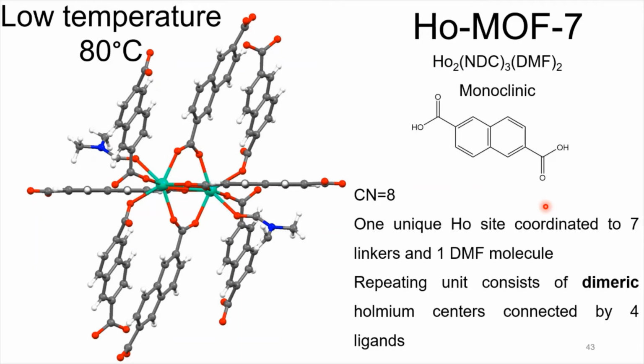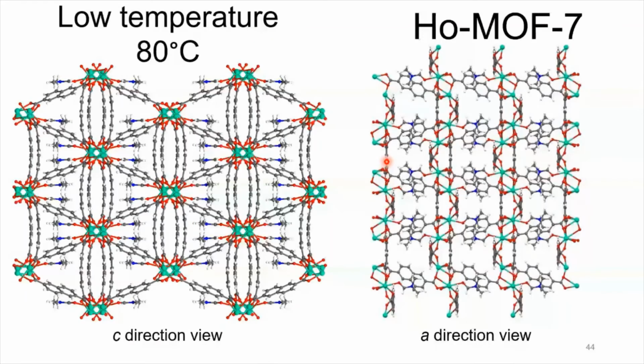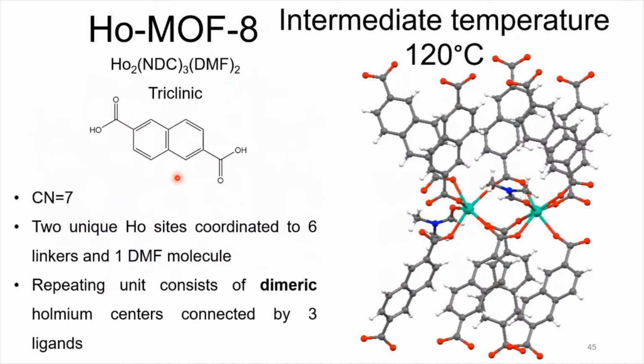And again, the main thing we see is there's a dimeric cluster in the repeating unit, and the coordination number will actually change. So we have this final structure, which again doesn't look that porous, and we actually see some bending of this naphthalene, which was something that surprised us at the beginning. So we went there and we increased the temperature to 120, and just with this increase in temperature, we changed the coordination number, which again just led us to a change in the structure.